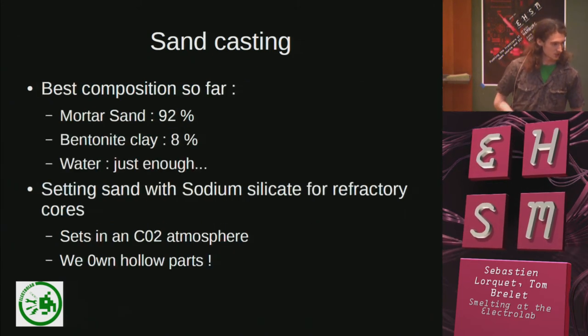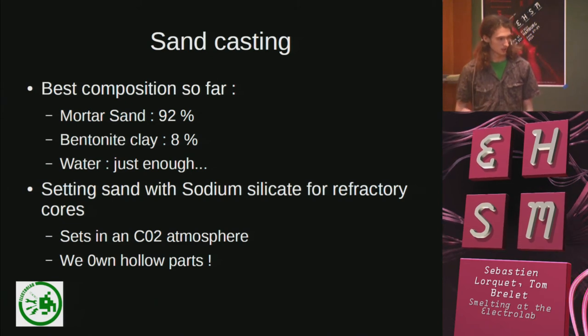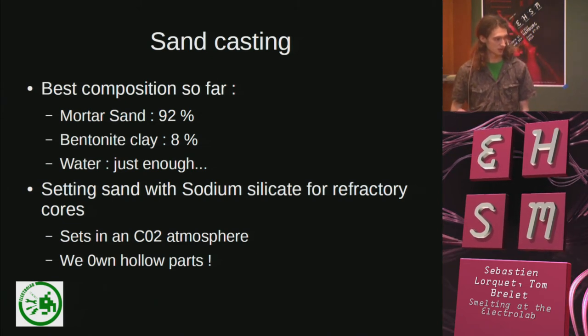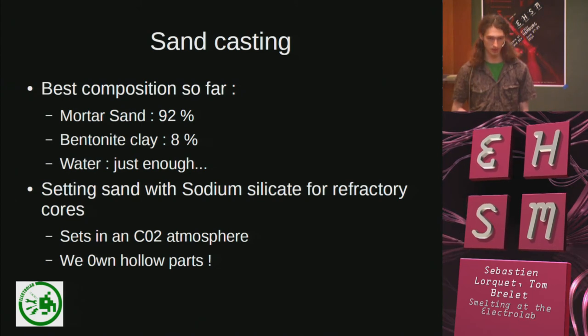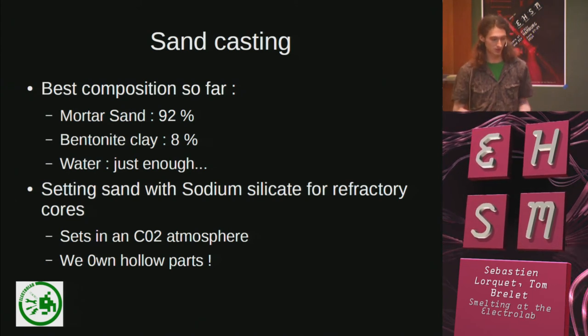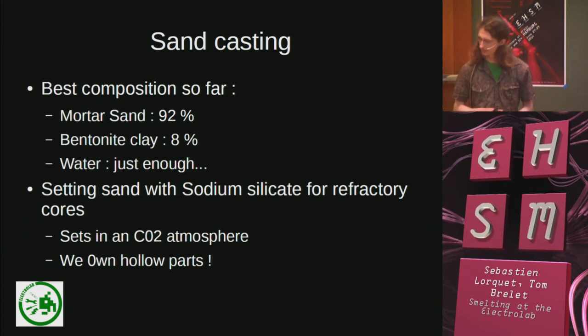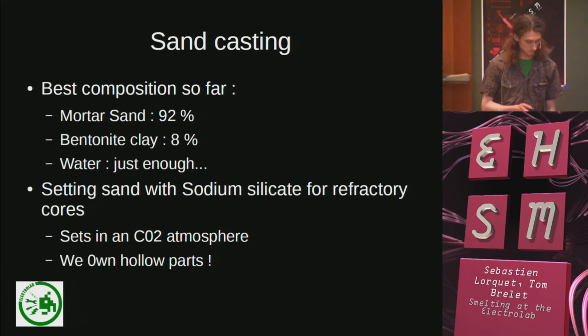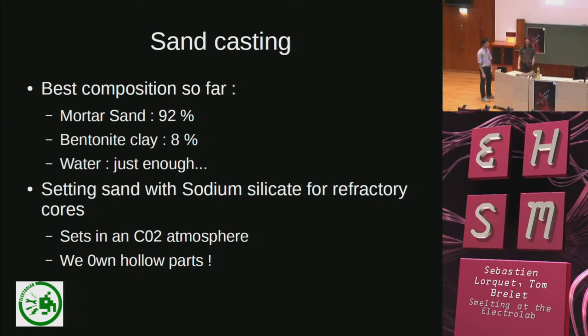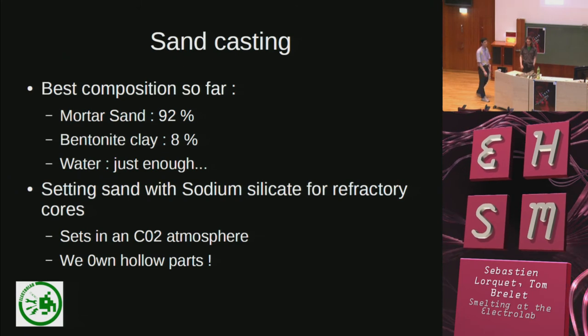The best composition we ever had is 92% mortar sand, 8% bentonite clay, and water. We don't quantify the water. We try to have the right cohesion. We try to get the best cohesion we could, so that the sand was not too wet, but we required a certain strength, more.